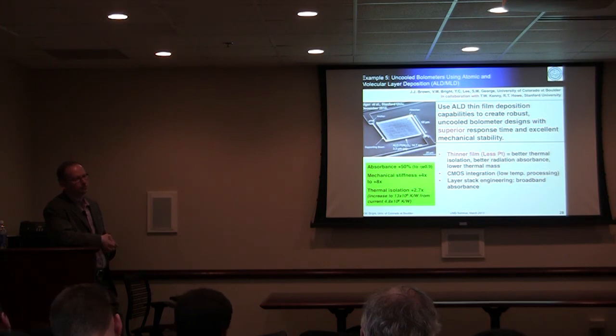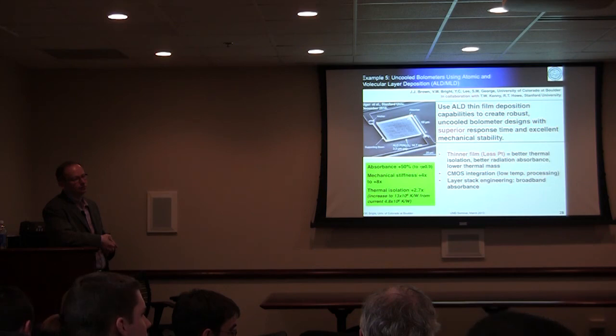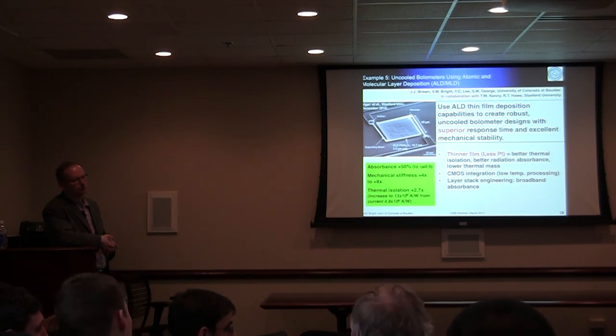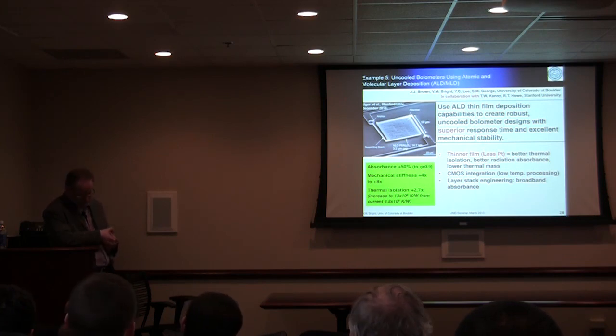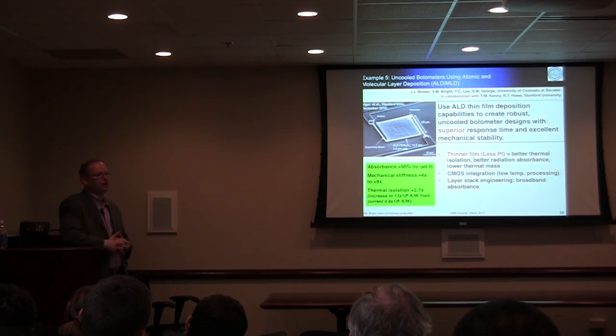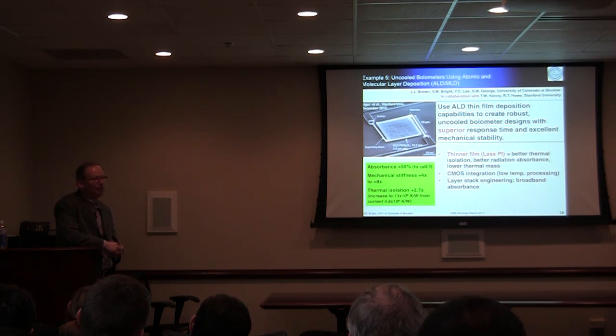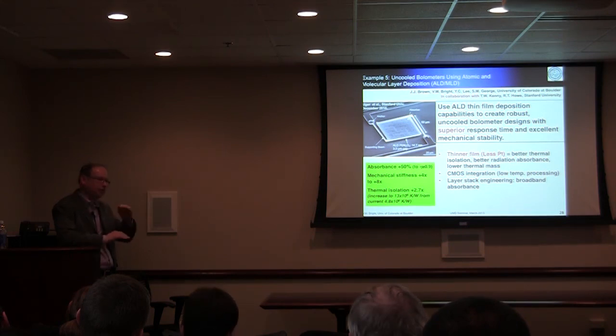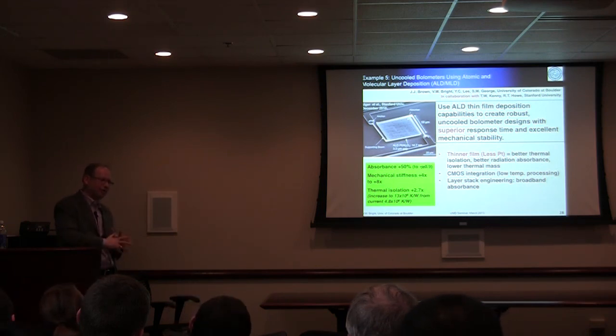You talked about composite ALD materials using multiple layers of inorganic and organic ALD. Does adhesion become a problem between these layers? And what would you think about the final conformality of the composite layer, the different inorganic layers? Well, the layers are conformal to each other. The topography of the underlying substrate would be less and less of a problem as you keep depositing more and more layers. Intuitively that makes sense, right? Whatever issues you had with topography would be gradually reduced.